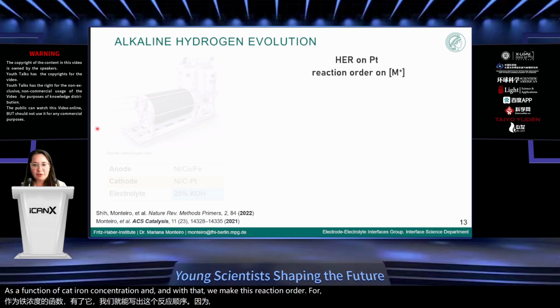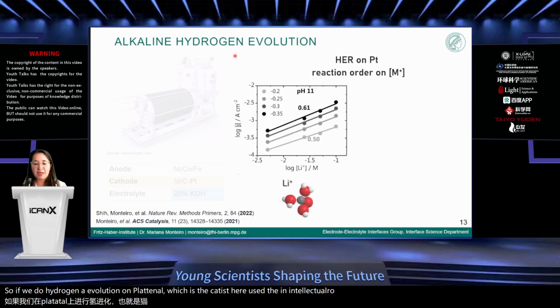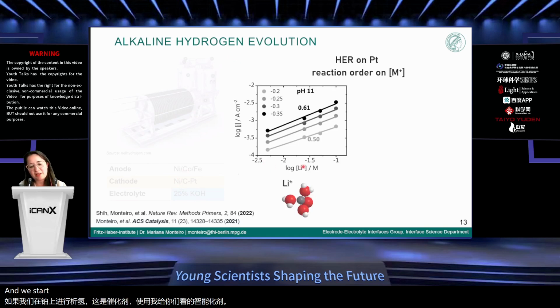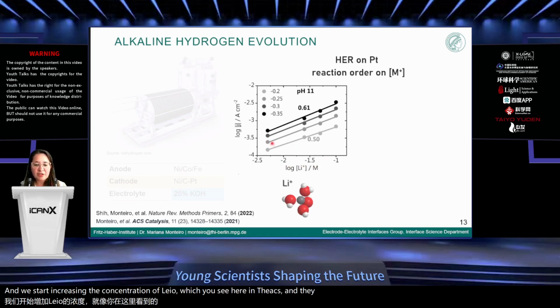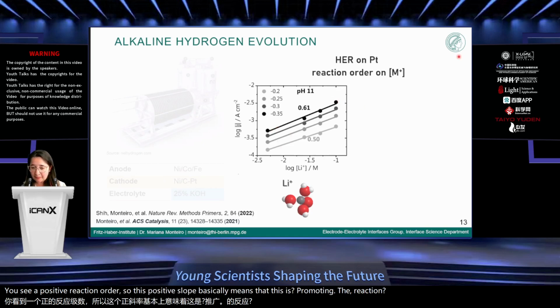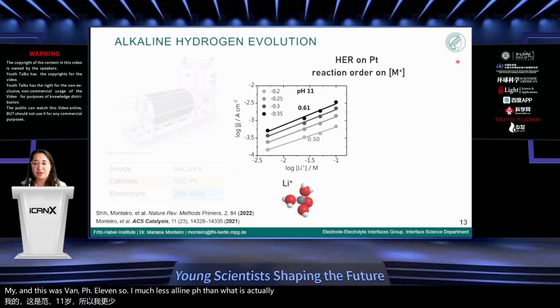So if we do hydrogen evolution on platinum, which is the catalyst used in the electrolyzer I showed you, and we start increasing the concentration of lithium, which you see here on the x-axis, in the electrolyte, you see a positive reaction order. So this positive slope basically means that this is promoting the reaction. And this was done at pH 11, so a much less alkaline pH than what is actually used industrially.